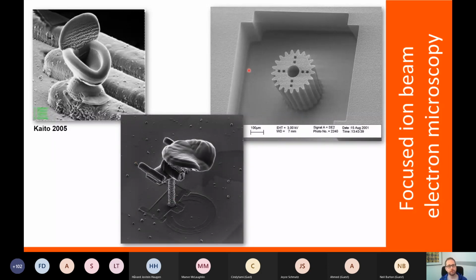But here on the right hand side, you can also see the precision of cutting into material. This here is a little device. This is about 100 micrometers here of cut into a material using the FIB. And I should also say that this gear here is about 200 micrometers in size. So you have a very powerful technique, not only using the electron beams to image materials, using secondary electrons to get topography, or backscattered electrons to get element contrast, or using X-rays. You can also manipulate material, cut into the material, or deposit material on top of your material.